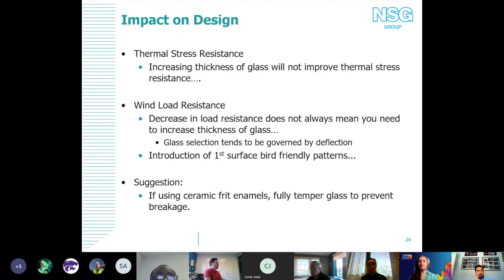for wind load resistance. And so my final note that I would say is, if you're using ceramic frit enamels, I would highly recommend just fully tempering the glass to prevent breakage. I know that leads to other associated risks, but otherwise you're really leaving yourself open to potential thermal fracture risk.